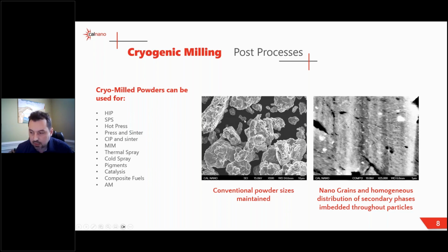We do that on purpose because in the case of light alloys and most metallics, if you decrease the particle size and you also don't have any oxide, that is a recipe for a very reactive material. And in many cases, it can become so reactive that it becomes pyrophoric, meaning that it'll just spontaneously combust as soon as it meets oxygen for the first time. So in our world, we prefer not to make nanoparticles. And in the case of reactive materials, we go through great lengths to make sure we don't. We get the properties of nano without having to deal with the dangers of the nano.